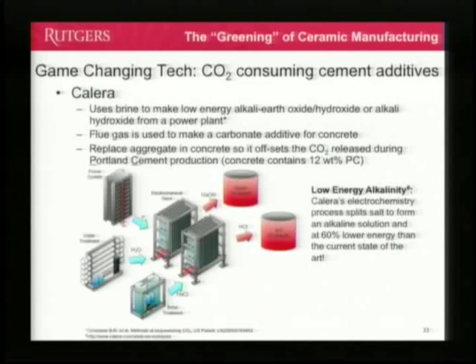But I still don't think their calculation is right. They've placed no numbers on what the CO2 footprint is for making the alkaline earth hydroxide. They have to do this. You cannot take cations out of seawater unless you raise the pH to at least 13 or 14. And then the process of precipitating the solids lowers the pH back to 7. It's a neutralization reaction. So for every mole of material they want out as a carbonate, they're going to have one CO2 neutralized by a sodium hydroxide. So we'd like to see what that number is.